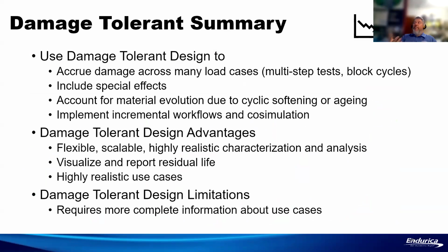If you've got multiple load cases like block cycles or multi-step tests, if you've got aging or cyclic softening, that causes material evolution. And anything that is an incremental type of workflow or a co-simulation, that's when you would use damage tolerant. We recently published a paper on modeling the effects of oxidation on fatigue, and that's another example where we would use this incremental workflow because the material properties are changing with time. So obviously you can be very highly realistic in terms of material properties and in terms of your duty cycle. The only limitation really is that you've got to specify things more completely, and there's some more work for the analyst to do around tying everything together to build the workflow.